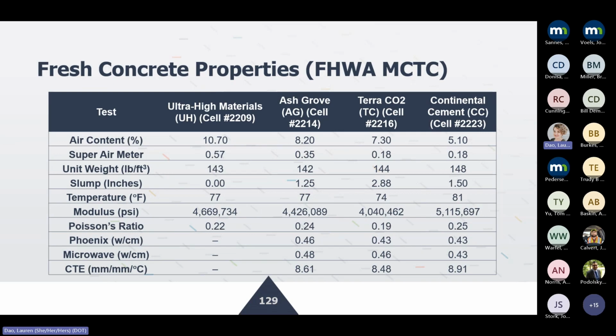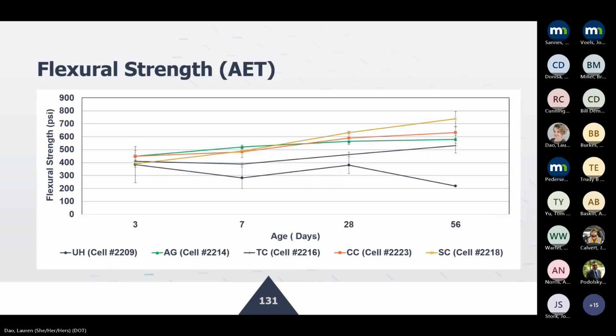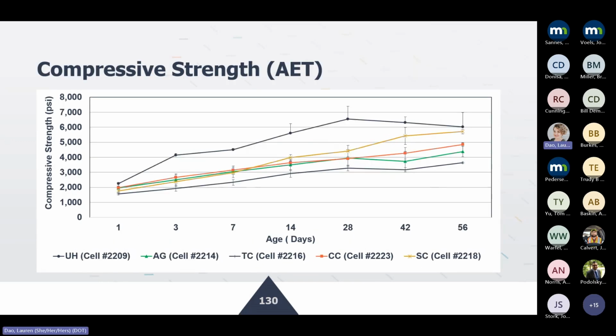And then looking at the modulus values, very, very similar, in the 4 to 6 million PSI range. And the Poisson's ratio was also in the 0.2 range, which was very, very typical of what you would expect from your paving mixture. And then quickly looking at the compressive strength results, as you can see, some of these materials have a slightly lower rate of strength gain, particularly the one at the bottom that you see. I believe that's the Terra CO2, which had, I think, 35% replacement, but slightly lower rate of strength gain, but overall, nothing out of the ordinary.